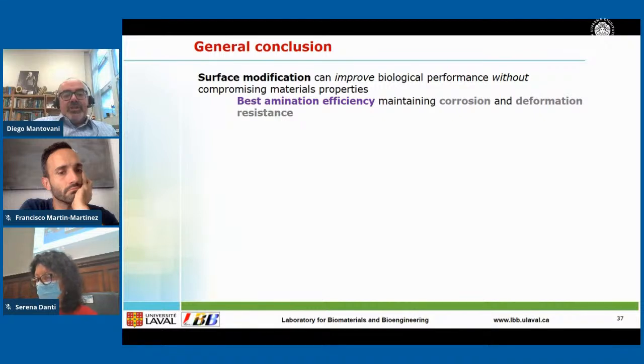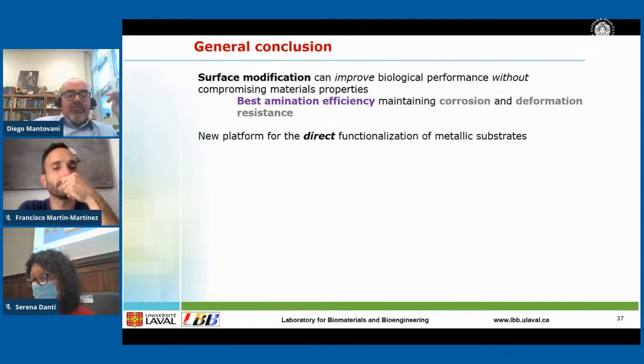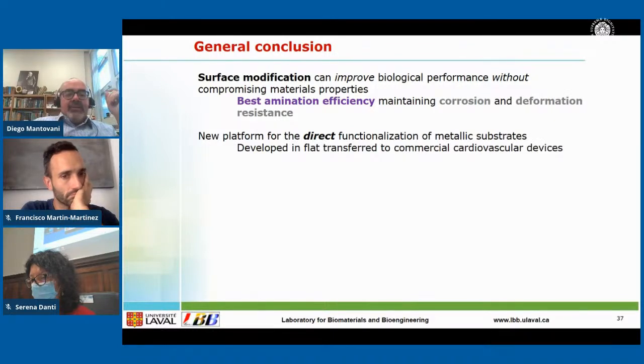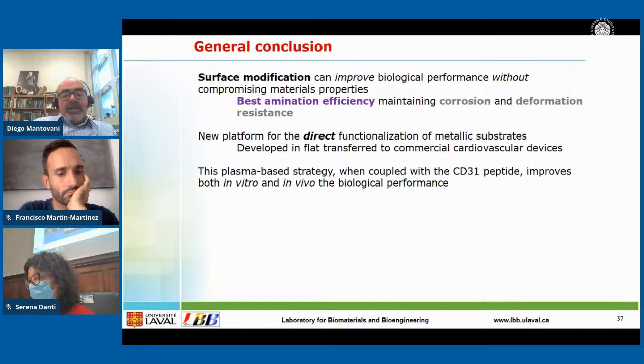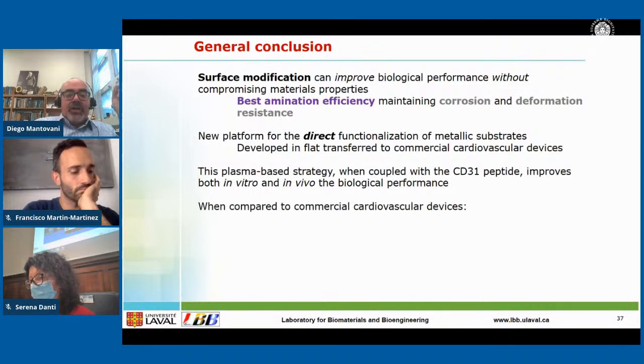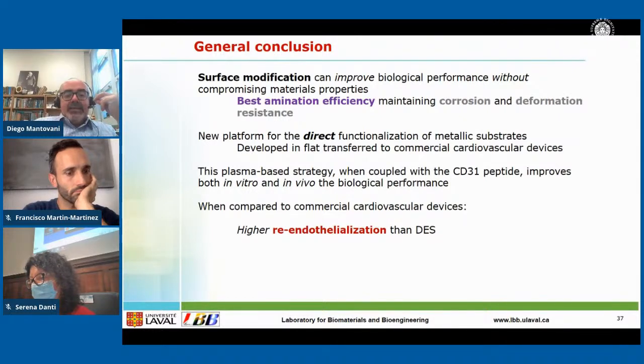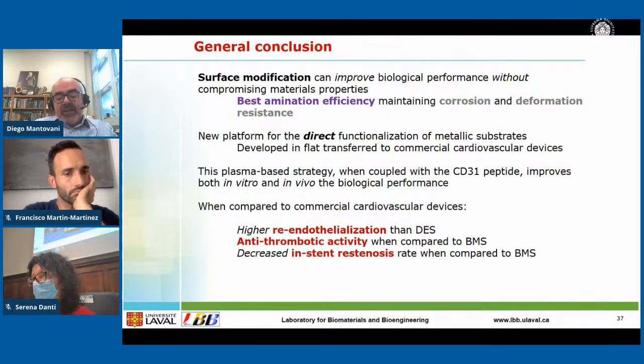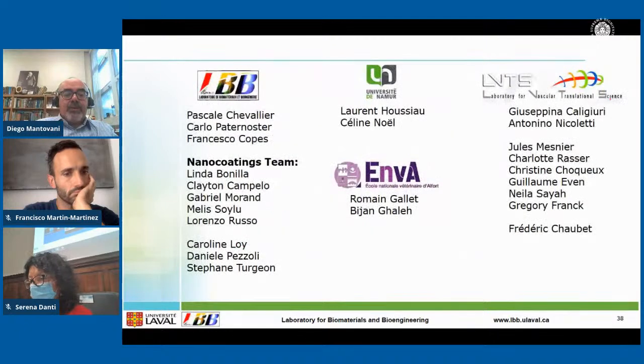So in conclusion, surface modification can improve the biological performances without compromising the material properties. The best amination efficiency was observed while maintaining corrosion and deformation resistance. This developed a new platform for the direct functionalization of metallic substrates, and what was developed on flat samples was transferred to commercial cardiovascular devices and stents. This plasma-based strategy, when coupled with CD31 peptides, improves in vivo biological performances. And when compared to commercial cardiovascular devices, this peptide strategy induces a higher endothelialization than drug-eluting stents and antithrombotic activity, especially compared to bare metal stent. And finally, a decrease in in-stent restenosis when compared to bare metal stent.